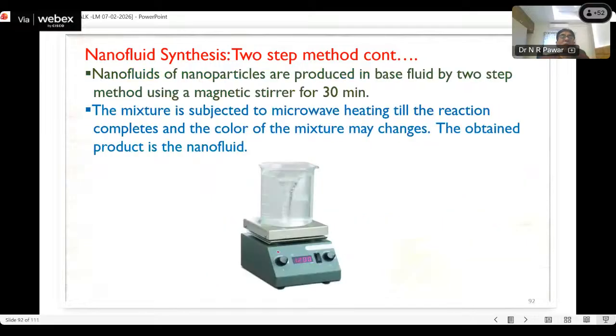Nanofluids of the nanoparticles are produced in the base fluid by the two-step method, using a magnetic stirrer for 30 minutes. Mostly in our laboratory, we have synthesized the alpha alumina nanofluid and boehmite nanofluid by using the magnetic stirrer. For the synthesis of the hybrid nanofluid, we used the research laboratory of the Department of Physics, RTM Nagpur University, and we synthesized the hybrid nanofluid by using ultrasonication techniques for the stirrer.